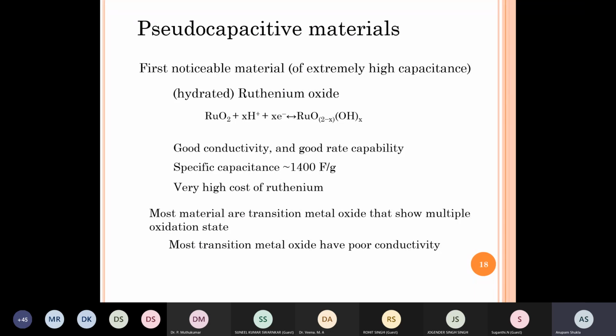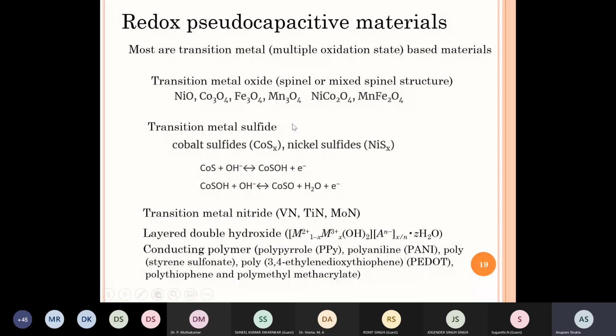At least the oxides have poor electronic conductivity, and that's one of the drawbacks of pseudocapacitive material. If you look at different mechanisms, we'll only look at the redox pseudocapacitance and the intercalation pseudocapacitance. Most are transition metal based materials. There are transition metal oxides which are of spinel or mixed spinel structure.